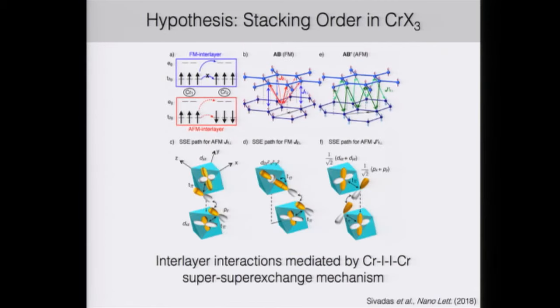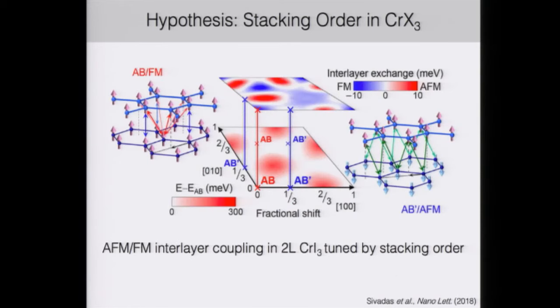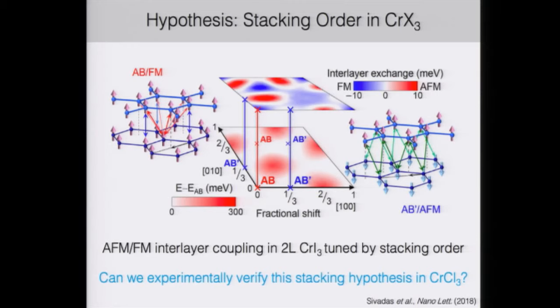And so the dominant term that will stick out is stacking. So there's a hypothesis that the stacking order in the chromium trihalides is what is giving rise to this difference in the interlayer exchange. So this paper published last year in Nano Letters considered calculations where you look at the interlayer interactions mediated by the chromium-iodine-iodine-chromium superexchange mechanism, or namely just the exchange between nearest neighbors of chromium sites across the van der Waals gap through the adjacent iodine ions. And what they found is that if you shear one layer with respect to one another in chrome iodide, you can actually tune between favoring a ferromagnetic or antiferromagnetic interlayer exchange based on the stacking between 2 layers. And so we wanted to ask the question, can we experimentally verify the stacking hypothesis in chromium trichloride?